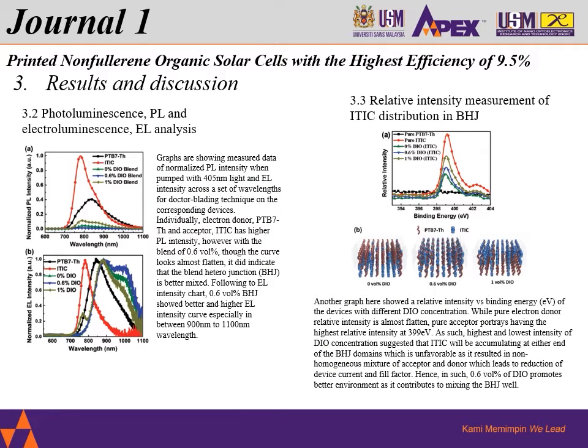Next, we'll go to the photoluminescence and electroluminescence analysis. So over here, we have a spectrum. At the top here is the normalized photoluminescence intensity, and the bottom one is the normalized electroluminescence intensity. And over here, what was reported out was the individual acceptor and donor purely by themselves, as well as the blend. The blend means the blend between the donor and the acceptor, with the addition of different concentrations of DIO.